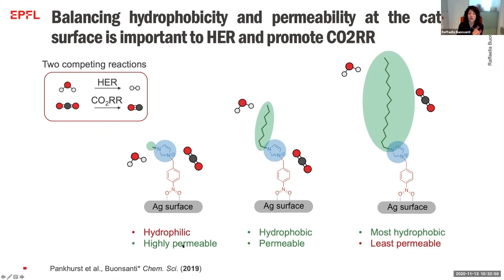And this is quite unusual because normally you would think that the shorter the ligands, the better, because they are highly permeable. So if they are shorter, your reactant molecule will be able to access the surface more efficiently. And ideally, maybe no ligands at all would be the best. Well, this is not the case, because the ligands here, in addition to controlling the permeability and the accessibility of the surface to the molecules, also have this tail length, which controls the hydrophobicity close to the catalyst. And so here, in the case of CO2, it turns out that having a certain hydrophobicity of this tail helps keep away the water molecules and promotes the CO2 reduction.